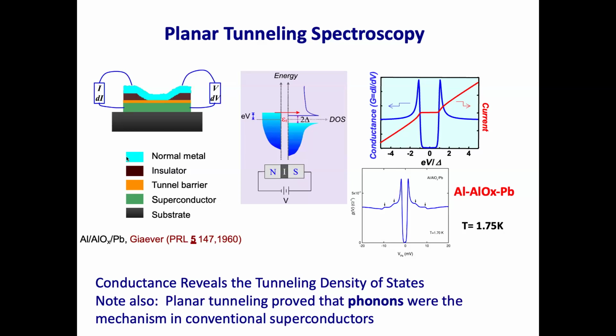But what's important to remember through this talk is that if you measure neutrons, and by the way, these 6 and 8 millielectron volt phonons were measured in neutrons, and then they saw them in the tunneling. And Macmillan was able to go back and forth and say, oh, these are part of it, and they only show up when it's superconducting, and do some other calculations. So if you have excitations that you could measure with neutron scattering, whether it's spin or phonons, you should see it in the tunneling if it's part of the mechanism.